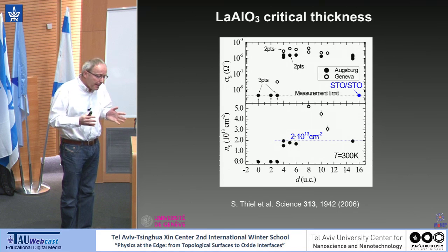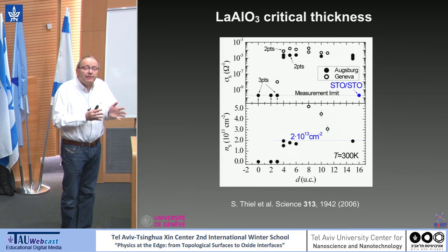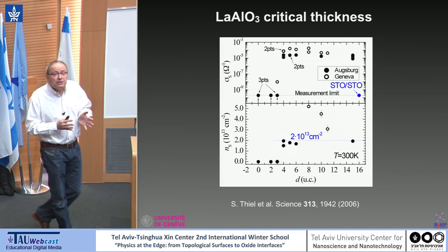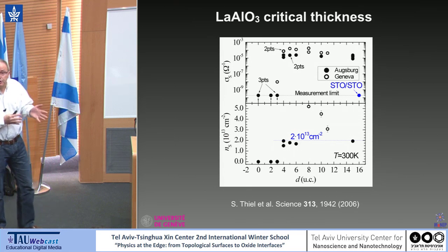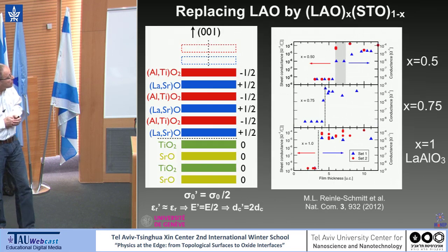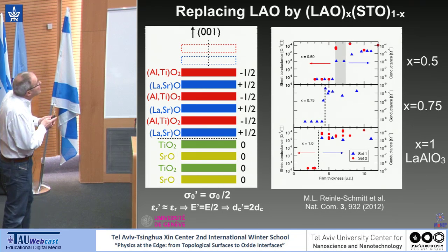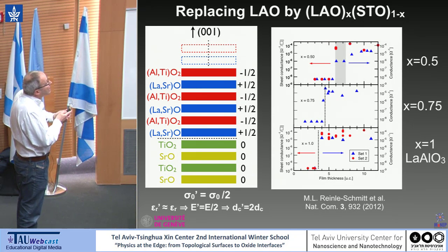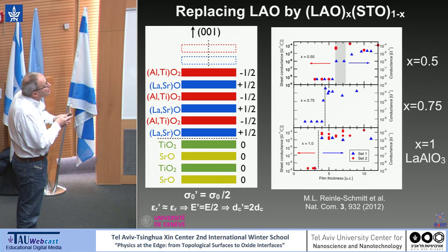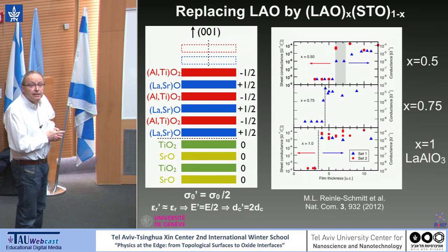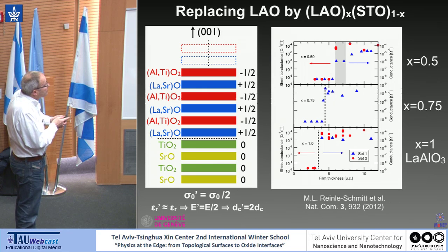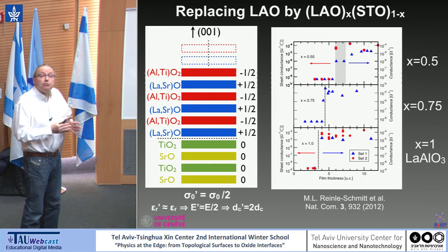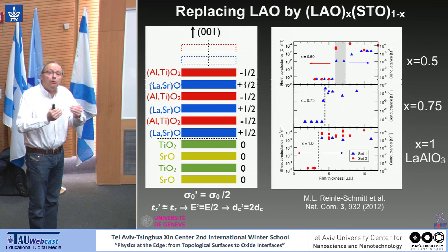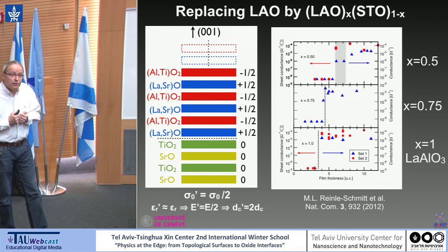And the idea was, can we tune the level of the polar discontinuity and check the prediction for the critical thickness? And what we did was, in fact, quite simple. We replaced lanthanum aluminate by an alloy of lanthanum aluminate and strontium titanate. And if you take 50-50, you realize quickly that instead of having +1, -1, you will have +1/2, -1/2. So you lower the level of the discontinuity.